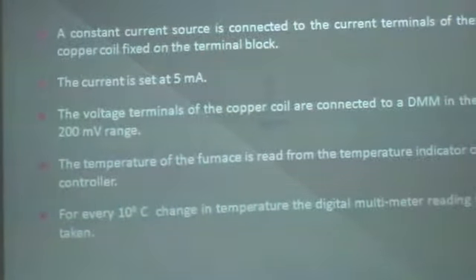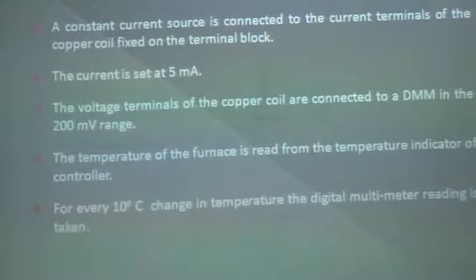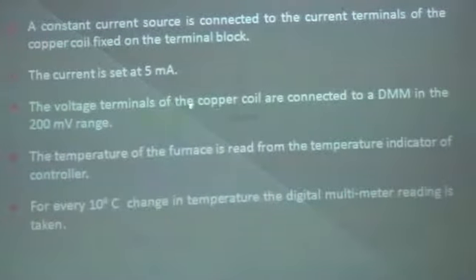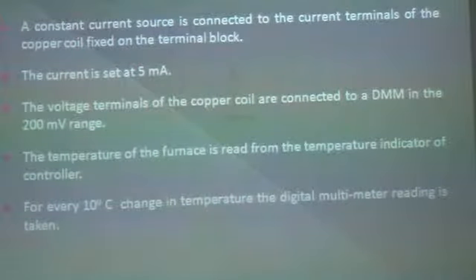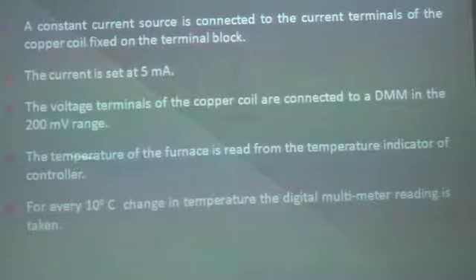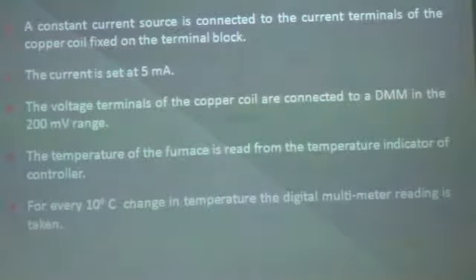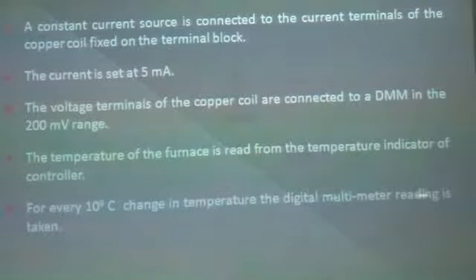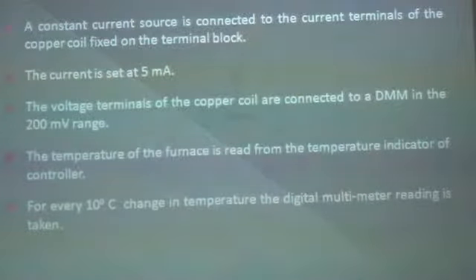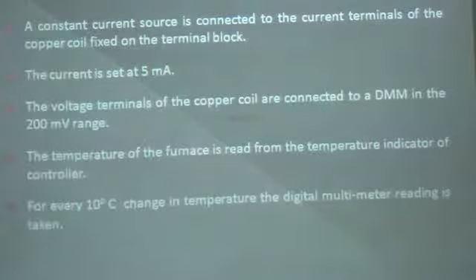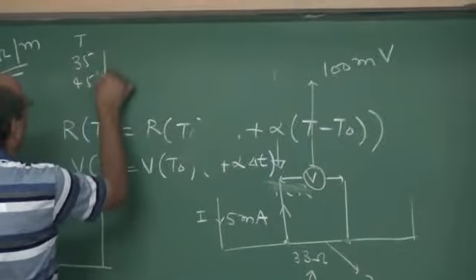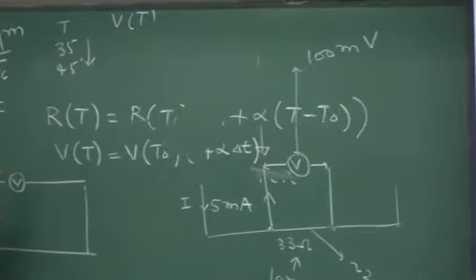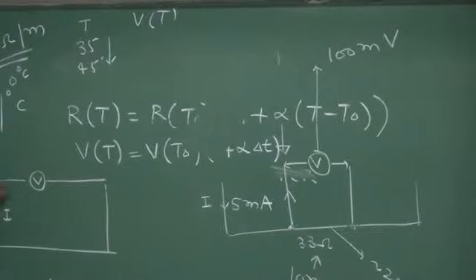We connect a constant current source to the current terminals of the copper coil fixed on the terminal block, the two extreme ends. The current is set to 5 milliampere. The voltage terminals of the copper coil are connected to a digital multimeter, so we connect a digital multimeter between these two ends. The temperature of the furnace is read from the temperature indicator of the controller. For every 10 degree change in temperature, the digital multimeter reading is taken. So we are recording the temperature, 35 degree, 45 degree and so on, and the voltage at temperature T. Finally, once we take these readings, we are going to plot a graph with the temperature on the x-axis and the voltage on the y-axis.